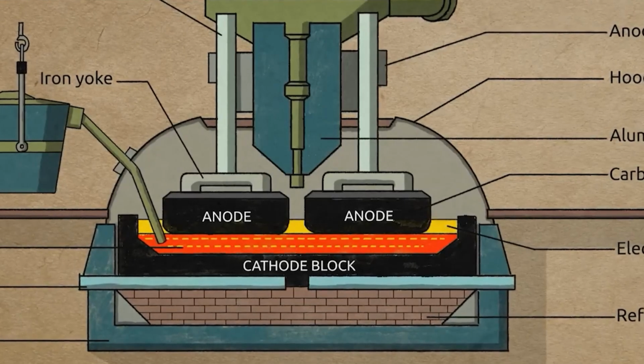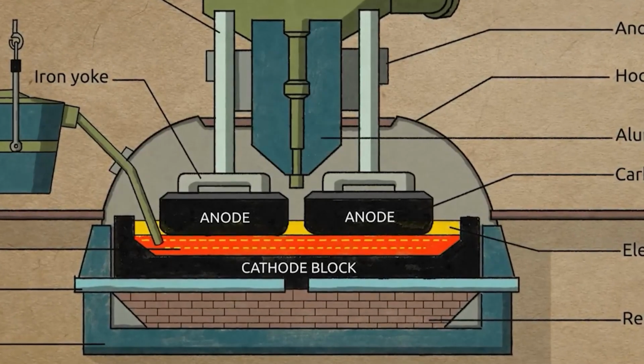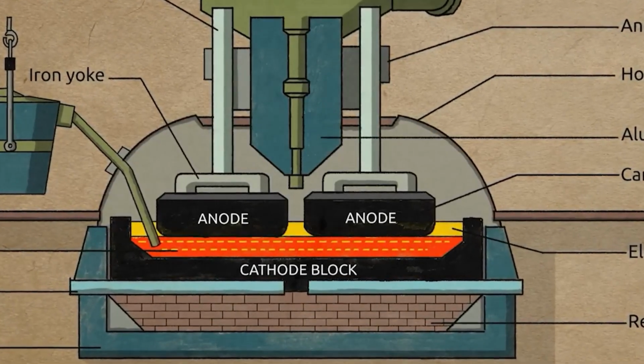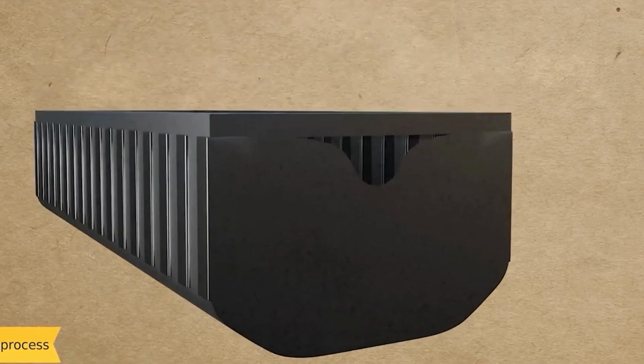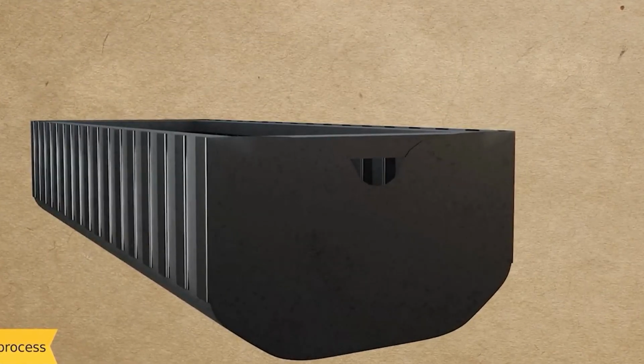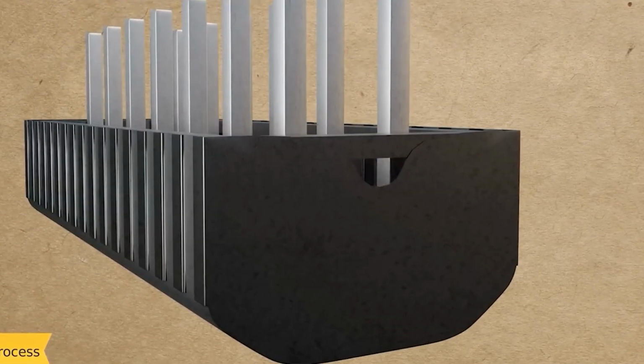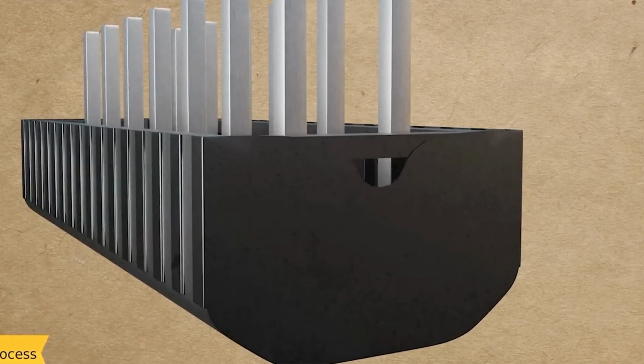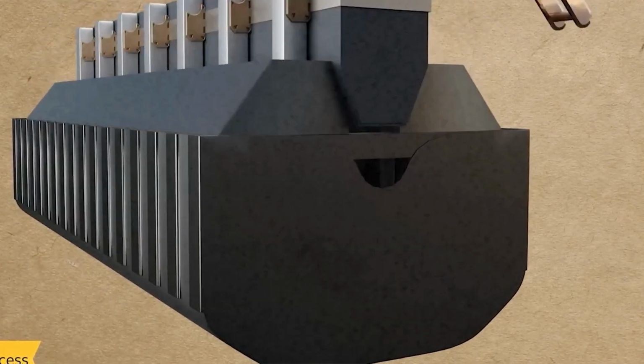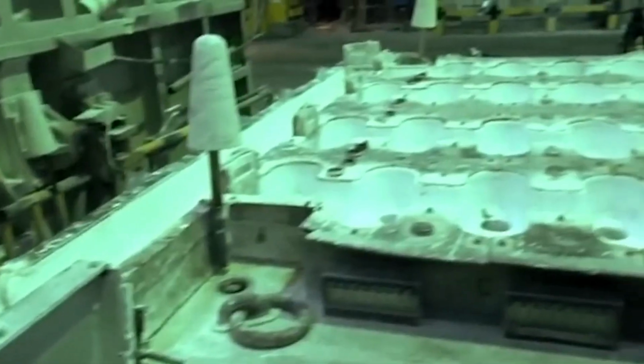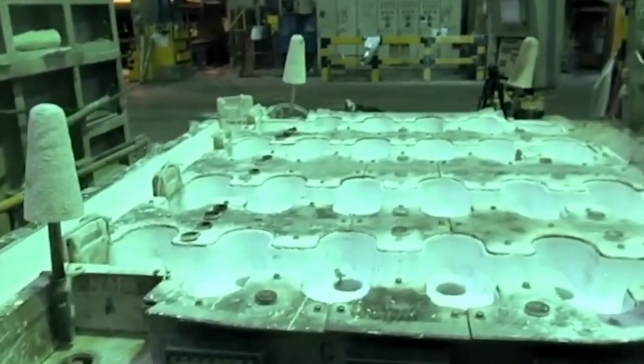These anodes remain about 1.5 inches, 3.8 centimeters, above the surface of the molten aluminum. The reduction pots are arranged in pot lines, each consisting of 50 to 200 pots connected in series to create an electric circuit. A single pot line can produce between 66,000 and 110,000 tons. Within the reduction pot, alumina dissolves into molten cryolite at extremely high temperatures, ranging from 1,760 degrees Fahrenheit to 1,780 degrees Fahrenheit.